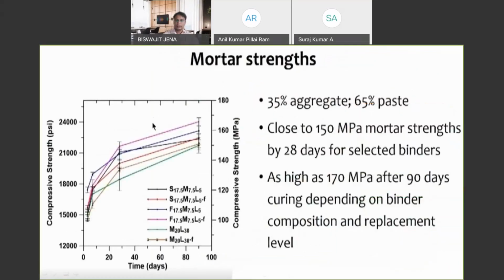Next we will go to the mortar strength. We did mortar strength, and you can see that we can get up to 150 megapascals strength after 28 days. This is 35% aggregate and 65% paste. You normally see it the other way in mortars and concrete. You need that amount of paste to satisfy the workability and the strength criteria, and we get 170 megapascals after 90 days with all these mixes which have 30% cement replacement. So that is fairly good.